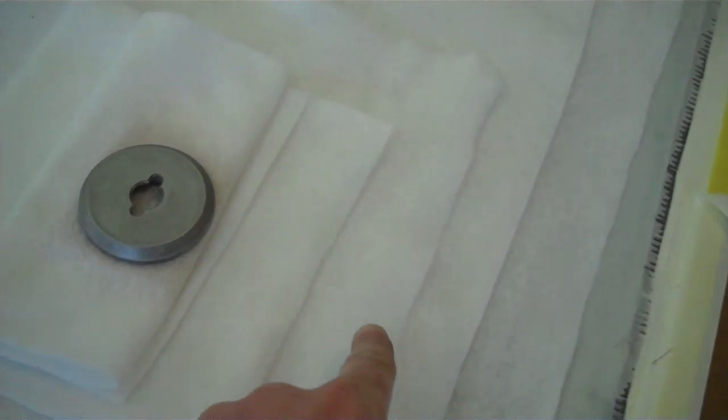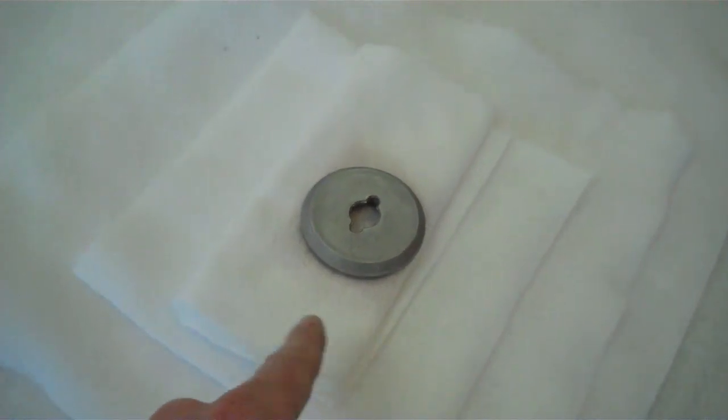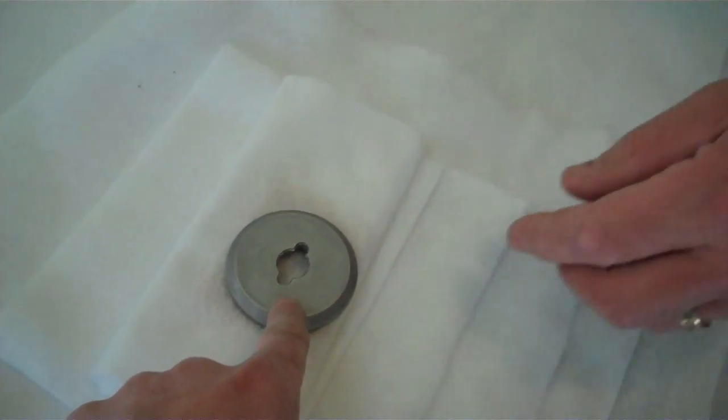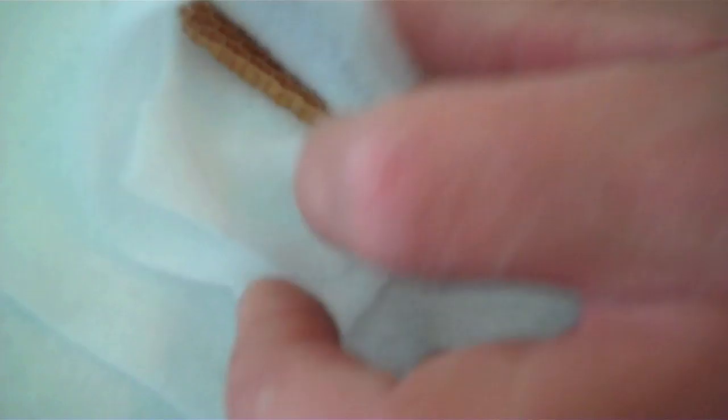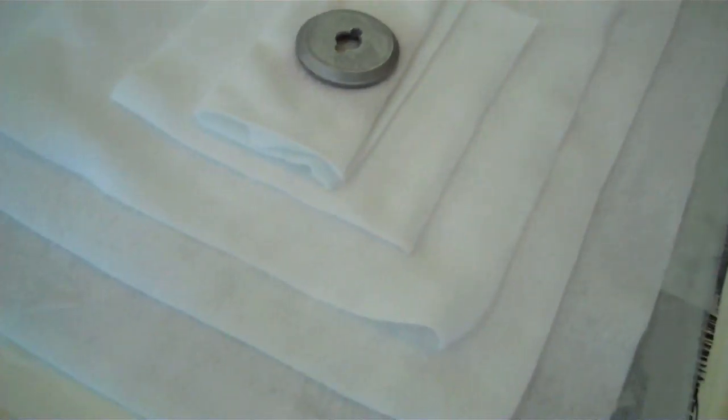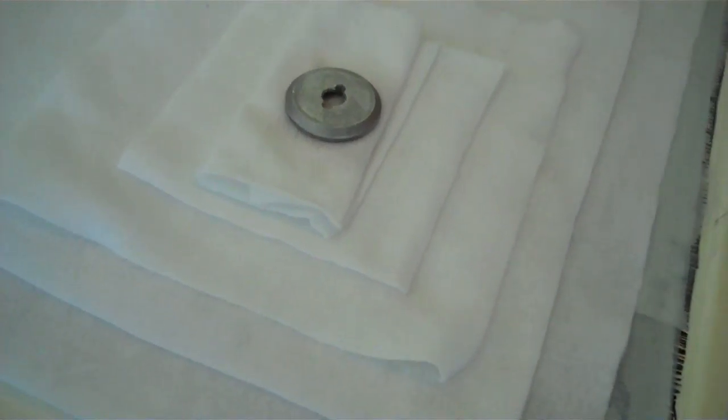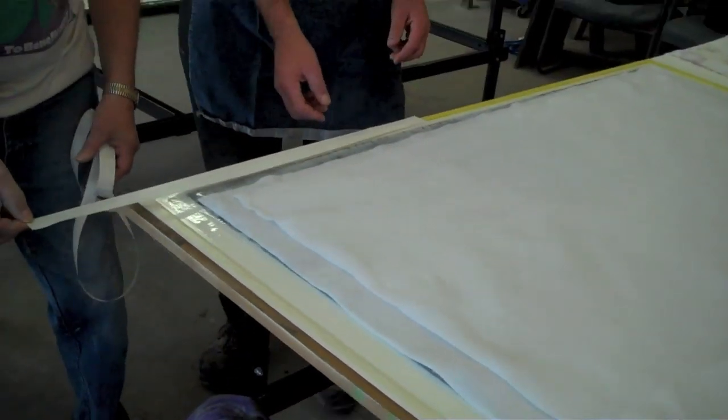And right here you can see there's multiple layers of bleeder material getting thicker and thicker. The last one's just a scrap piece that's folded over about three times and we put our puck down. And there's a piece of honeycomb in there so that it doesn't lock down. Otherwise it'll lock down and vacuum lock itself and you won't get any suction over here. You can use cardboard but honeycomb is better. Honeycomb is much better.